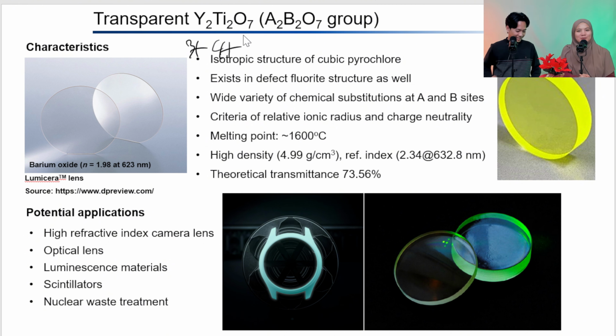So depending on the kind of elements, it can produce different materials. But I studied this transparent yttrium titanate, and you see it also has a cubic structure, and basically it can be substituted with different A and B, as long as A is +3 and B is +4. Right? Correct. And the melting point is quite low, compared to another ceramic. But compared to metal, it's still high. Because alumina is around 2000 degrees Celsius, so it's quite low.